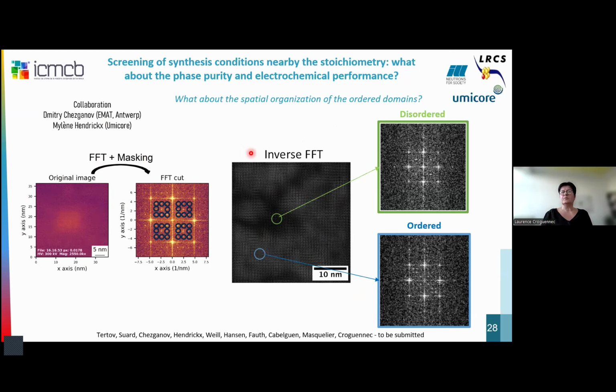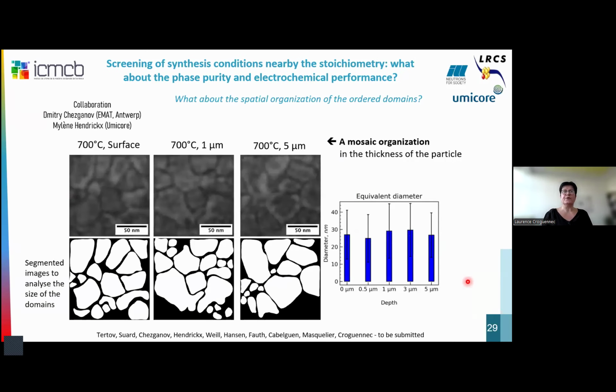And they were really able to show that we had in our materials some areas where, as shown here by the electron diffraction pattern, we are in a disordered area, meaning indexed by the Fd-3m space group. And here we are more in an ordered area, where we have these additional spots showing that we are in the P4332 space group. So what does it mean if we go further?